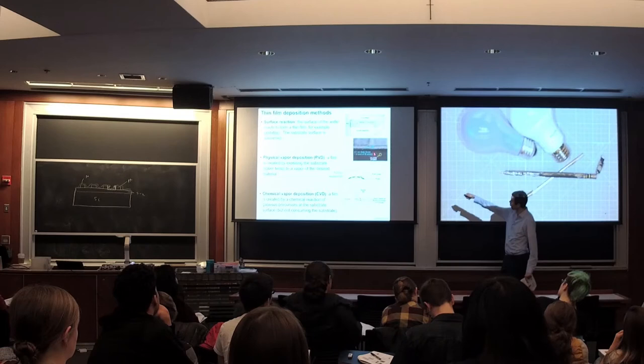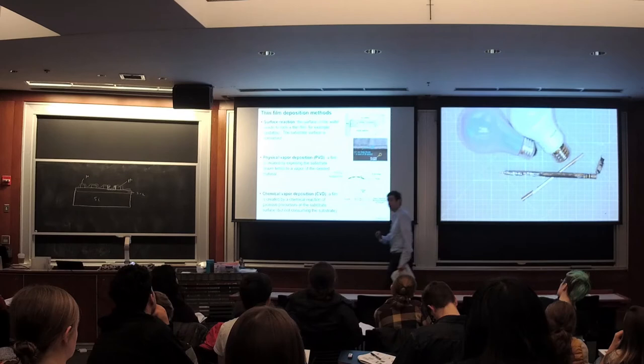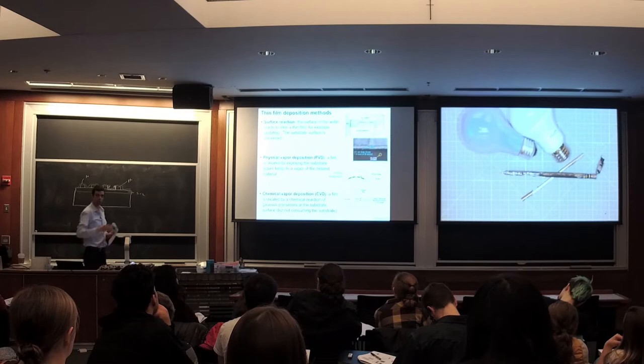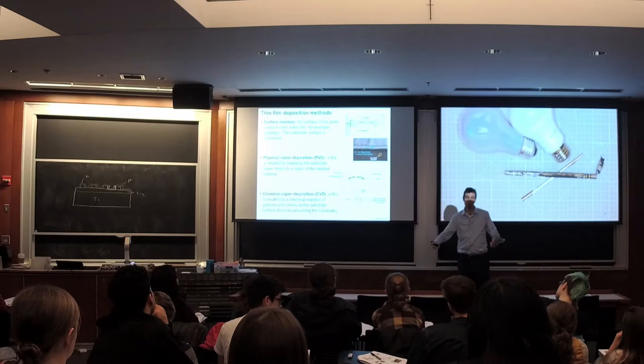This is an atomic resolution microscope picture taken using a special microscope where that thin oxide layer is like four rows of atoms thick. And companies that make this equipment can actually basically go down to single atomic layer precision over wafer areas that are 12 inches. And this is because they know how to control the rate of these deposition and reaction processes extremely well. They're very slow on a macro scale, and also because they have equipment that makes the temperature and the gas flow incredibly uniform, because all of these reactions depend on temperature.